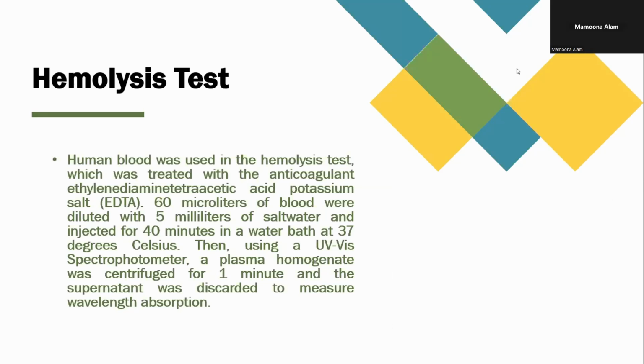The first test I performed was the hemolysis test, to see if the blood can be safe in the PVC and chitosan biocomposite membrane, which can further be used for blood bags. I withdrew human blood, which was treated with EDTA so that it cannot coagulate outside the body. 60 microliters of blood was taken and diluted with 5 milliliters of salt water and placed in the water bath at 37 degrees Celsius because human body temperature is 37 degrees. Then we used a UV visible spectrophotometer to centrifuge the plasma homogenate for 1 minute. And the supernatant was discarded.